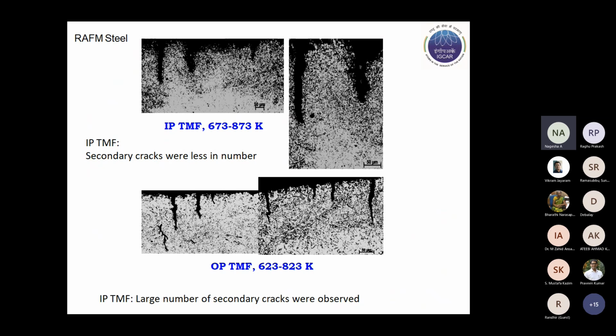And there is also another factor which is leading to lower cyclic life under OP, in the form of extensive cracking that is noticed under OP TMF in comparison with IP. In the case of IP loading, the cracks were fewer in number, and the tips were relatively blunt compared to the out-of-phase cycling. Here there was a higher density of surface cracks, and the tips were found to be much sharper compared to the IP loading.